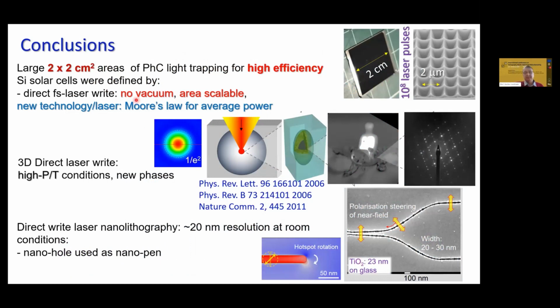I showed different applications. The key point is that now we can really think about large area applications. So centimeter square areas for photonic crystal light trapping becomes a reality. So direct femtosecond laser writing is useful because it has no requirements to have vacuum. Area is scalable. You can scan over large areas, and you can benefit from this very simple approach.